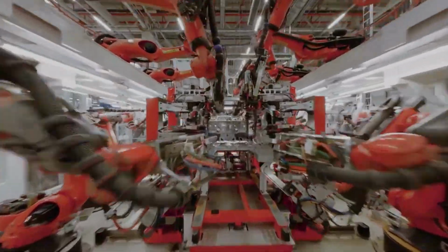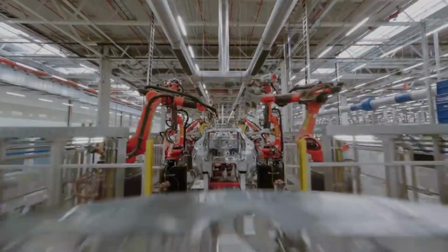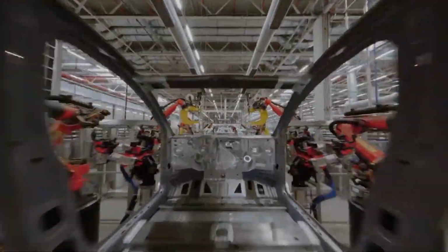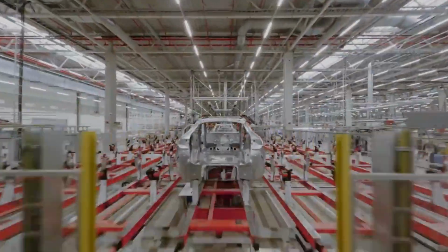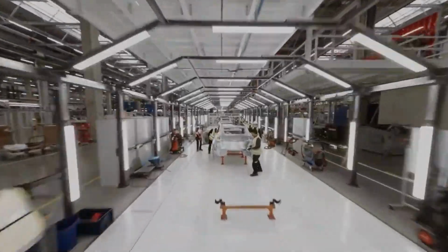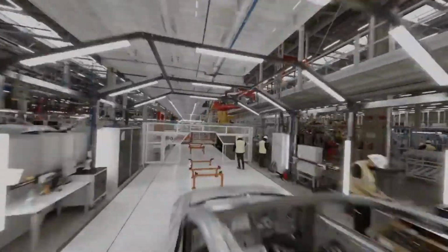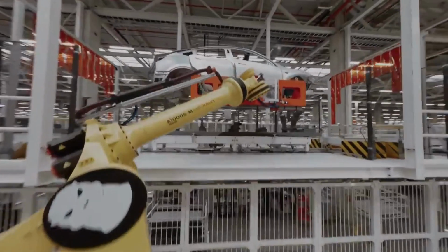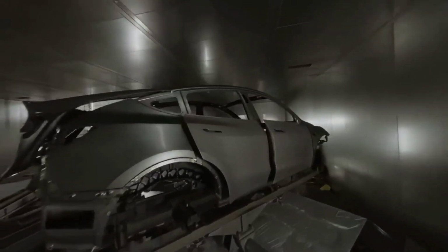After that, a quenching tank is used to quickly lower the raw casting's temperature from 400 down to 50 degrees C. It aids in eliminating some flaws and enhancing some material qualities. To get it ready for the next cycle, robots carefully clean the open die and cool it to 185 degrees C. Within 1 to 2 minutes of the current casting cycle ending, the next one will start.